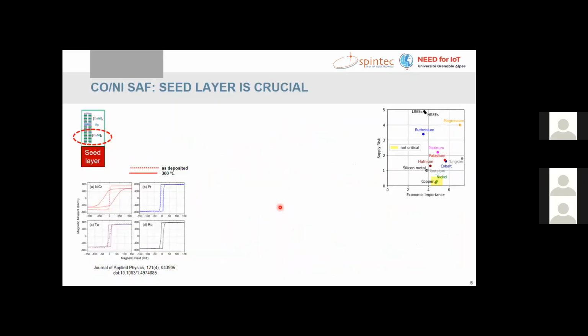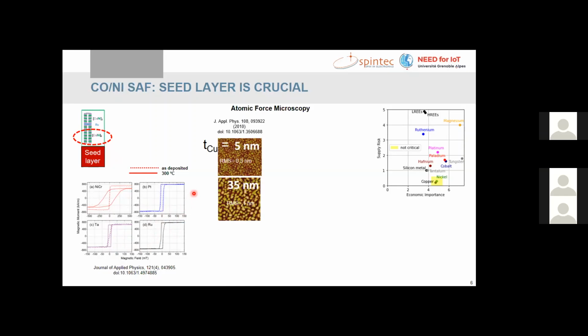So we have tried to target these issues, and we started to focus first on the seed layer, because for growing these multilayers, we need to have a very strong 111 texture. And it has been seen previously that the effect of the seed layer that you use is very important on the final magnetic properties of the multilayers. So ourselves, we chose to go more for a copper seed layer material, because copper is also classified as non-critical. And it has the advantage that it can also provide this 111 texture that we are looking for.